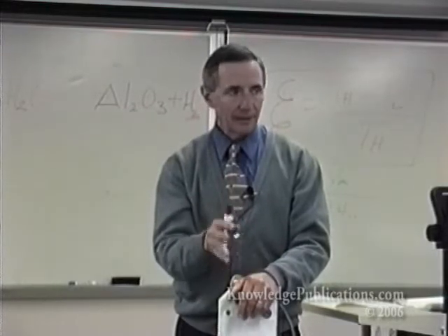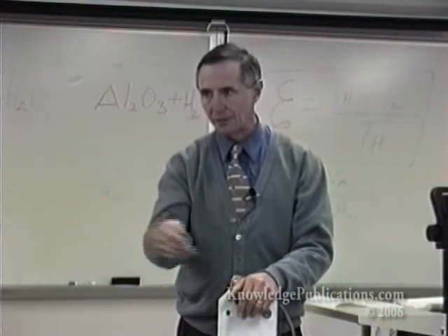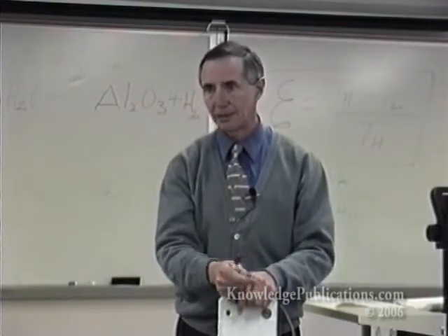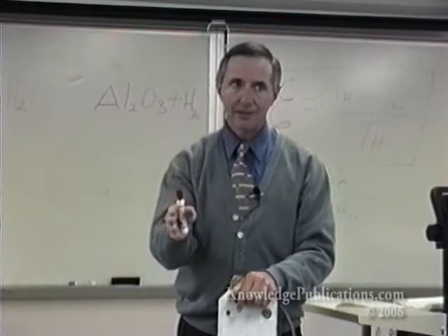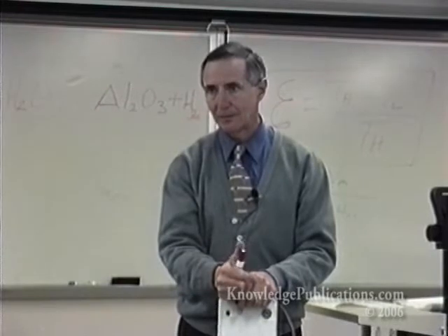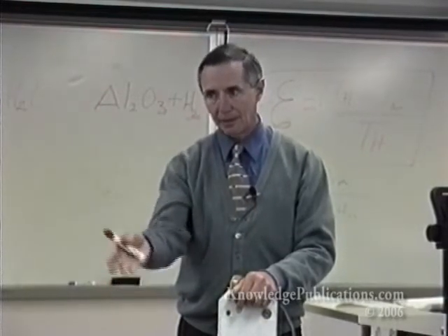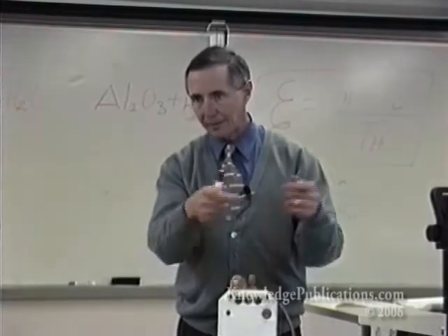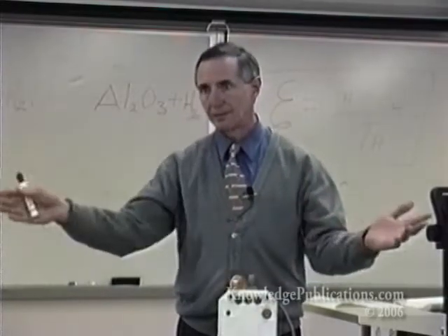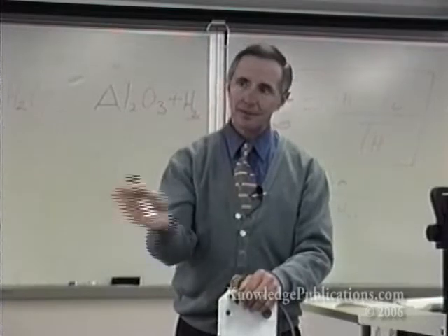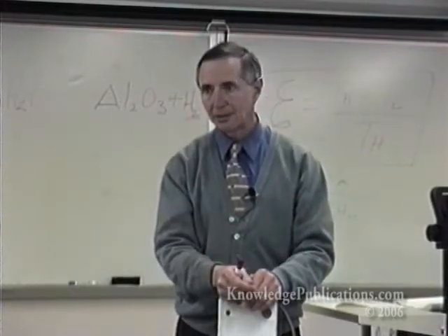Three, where they think they have ionizing potential, as in corrosion from galvanic or ground loops that use their system as a path, they must cancel that ion-producing or ionizing voltage with an adequate ground, and if necessary with a controlled application of voltage to make it null. If you do those things, the existing pipelines are absolutely adequate.